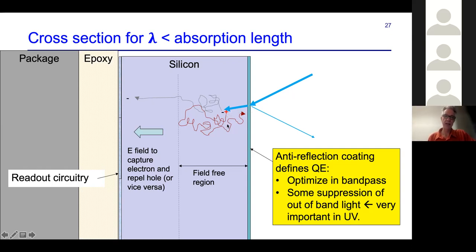And in that area, there's no electric field. And so the electron and hole just wander around by Brownian motion. And they may actually go in the wrong direction and get reflected off one of the edges. So it's very important that they not get stuck there. Shule is going to talk about some problems with that and the solution to those problems.